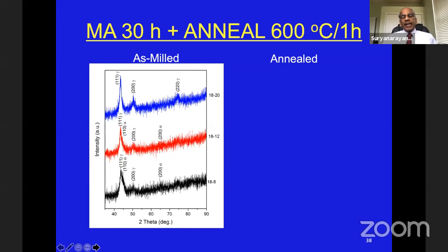Now, if you look at the austenitic stainless steels, as I said, typically you see 18 chromium and 8 nickel. But we wanted to study the effect of nickel content. And now if you look at the material milled for 30 hours, you can see the 18-8, that means 18 chrome, 8 nickel. You can see both gamma and some alpha, that means the austenite phase plus some ferrite. Increase the nickel content to 12%, the amount of ferrite has decreased. You increase the nickel content to 20%, there is no ferrite present at all, pure austenite.